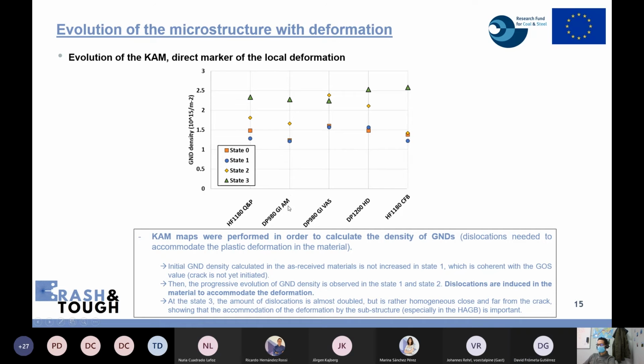Okay. And just to finish, in average, we calculated some GND density, and it evolves with the deformation, and we can have some quantified value of GND. So this can be some input for models. And we can say that at the stage 3, we have double the number of dislocations.